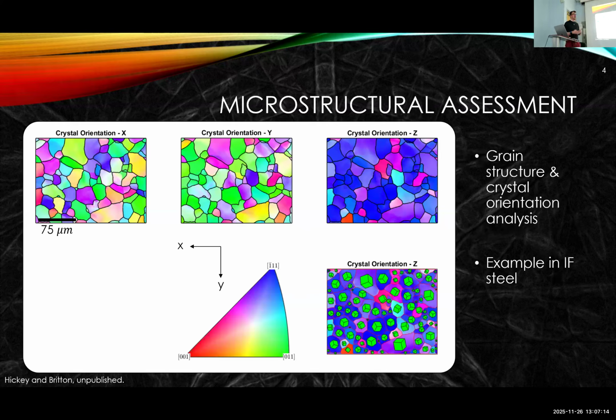So if we just look at one example of an EBSD map, this is a simple example of interstitial free steel. It's a fancy way to say we've got steel where we've locked up all the carbon, and this enables us to make the hood of a car beautifully shiny. You put carbon in the steel, it produces Lüders bands, and they put streaks in the front of your car, so you don't get paint adherence and other issues happen.